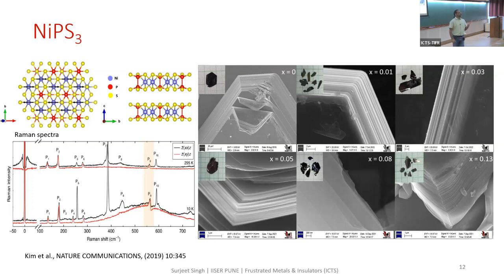It is very easy to exfoliate, all right? And the interesting thing, it's not our discovery, it is reported in this paper, that down to double layer, 2 layers, the magnetic ordering persists. In the monolayer limit, the magnetic ordering completely disappears. So our interest is, once again, as with RuCl3, to investigate the effect of non-magnetic disorder.